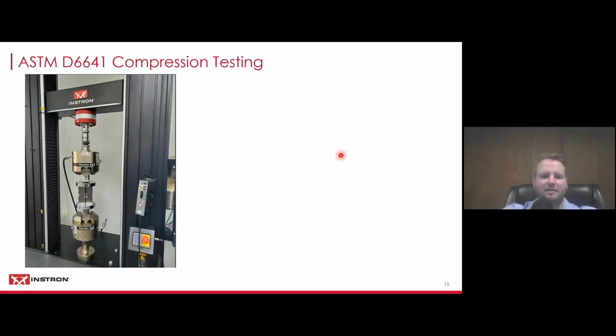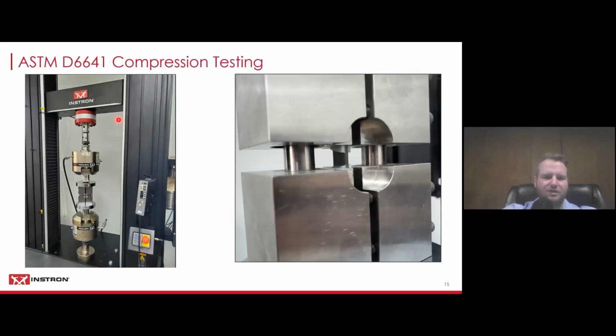We did run this test on one of our testing machines. You can see here we ran this on a floor model machine. We had hydraulic wedge grips installed. We did not want to remove those, so we utilized piggyback adapters to connect our compression platens, and then put the fixture in between the platens and ran the test that way.